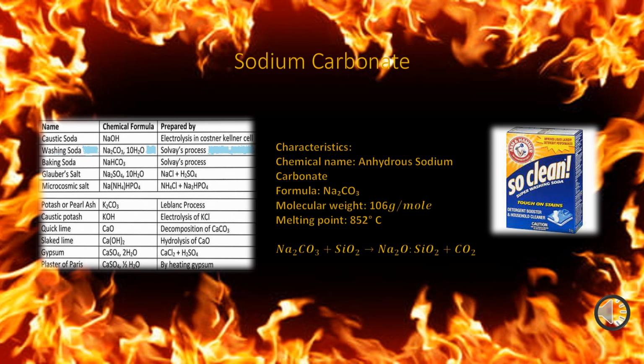Between 852 to 950 degrees centigrade, this material will not decompose appreciably. Above the 950 degree mark, it will start to release carbon dioxide. The point to remember is that it is a base and an acid is required. The acid is the silicon dioxide, which in turn forms the sodium silicate slag.